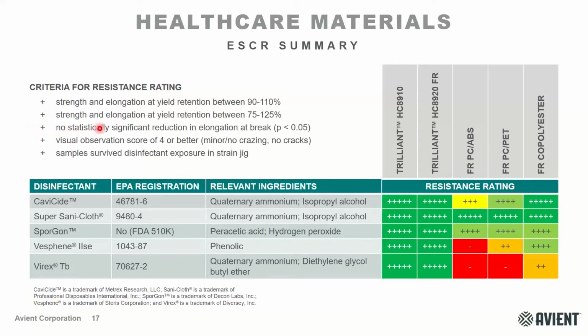So if there's no statistically significant reduction in the elongation at break on a 95% confidence interval, we'll give it an additional plus. And then the retention of the strength and the elongation and yield are also the other criteria. So can it retain between 75 and 100 or 100 and 125% of its original properties relative to the strain control? And then even a little bit more difficult, retaining 90 to 100 and 100 to 110% of the strength and elongation and yield. And so then we summarize this in a table.